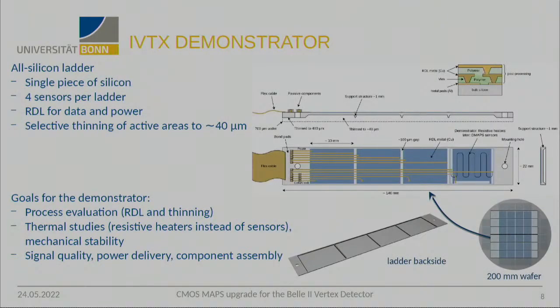We have a first IVTX demonstrator. For the innermost 2 layers, it's an all silicon layer, one single piece of silicon, with 4 sensors per ladder, and it's self-supported. We also have an additional redistribution layer for data and power, and the active area will be thinned down to only 40 micrometer to achieve 0.1% radiation length overall.